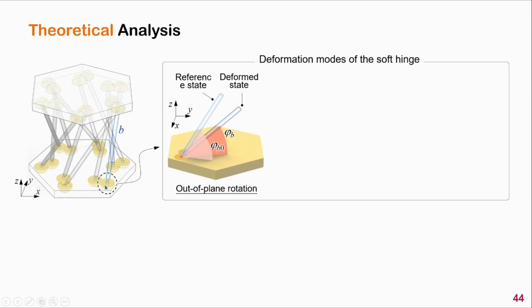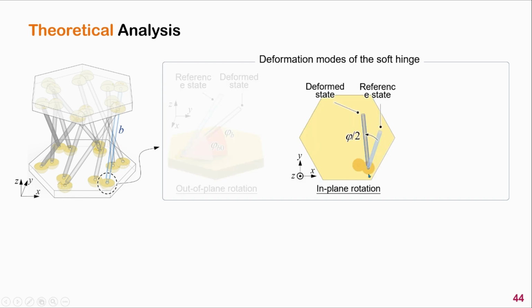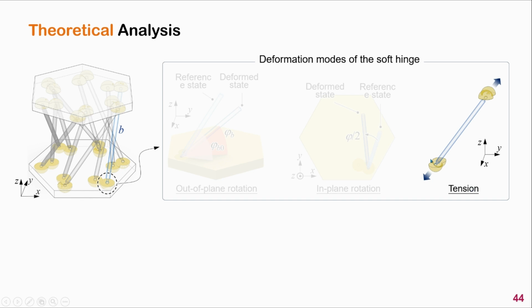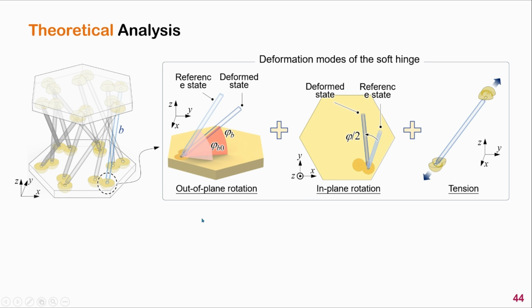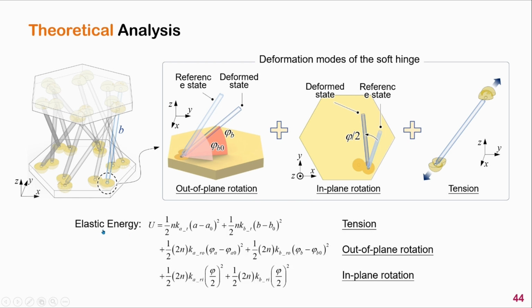Since the hinge is very soft, deformation will be highly localized at the hinge, and the hinge deformation can be decomposed into 3 modes. The first one is the out-of-plane rotation of the beam. The second one is the in-plane rotation of the beam. And the last one is the tensile deformation along the beam. In this manner, the total mechanical potential energy can be written as shown here. And there are 3 parts corresponding to the 3 deformation modes respectively.